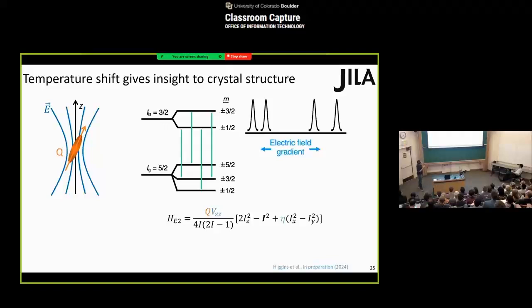So we've seen this quadrupole splitting. Essentially, this quadrupole interaction Hamiltonian gives us a splitting between the transition lines dependent on the local electric field gradient. But we also have a monopole interaction, where the finite charge radius interacts with the local electron charge density, and this could shift all the spectral lines together.